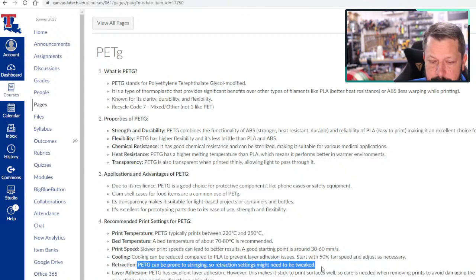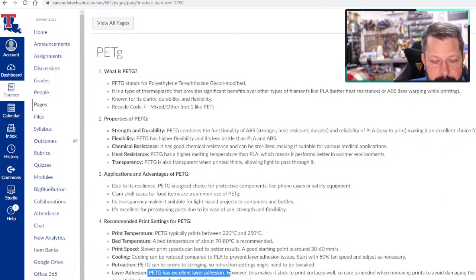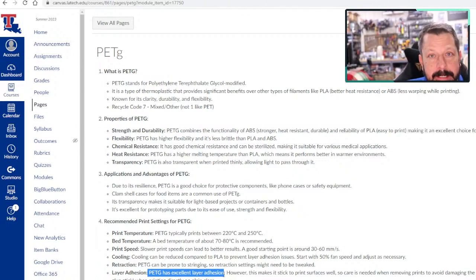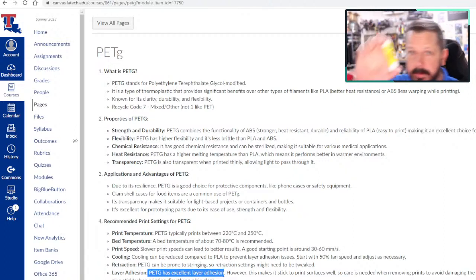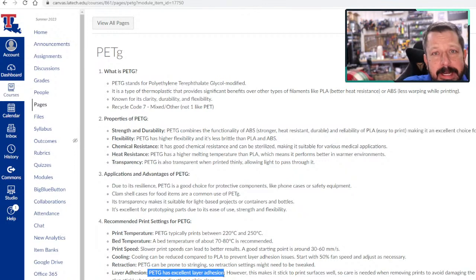Retraction, it is stringy, so you probably are going to have to set up your retraction settings for PETG differently, a little more aggressively. Layer adhesion, when it's printed without 100% cooling, is really good. That's because it's staying gummy longer, which is also why it strings, and so it sticks together pretty well. But one downside is it can stick too well to your print surface. So it is generally good practice to print PETG on a surface that you have some glue stick on, or hairspray, something that'll act as a release agent.